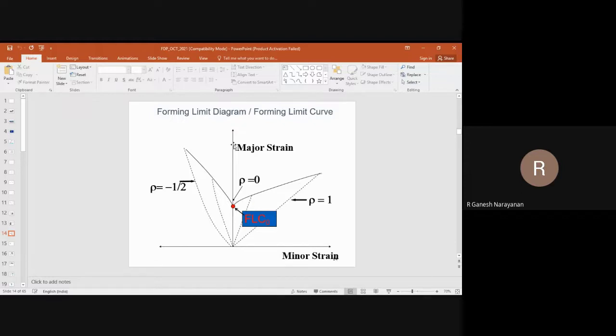Okay, once you are above this curve, you have a problem. The material can have definite physical failure. This FLC0, which I am focused on here, is nothing but one particular mode of deformation, that is plane strain mode of deformation. The limit strain in plane strain mode: if you pick up the y-axis, you will reach the red point here. Beyond that, if you deform along that y-axis itself, where minor strain is 0, you will have failure. This is the least window you have in the entire forming limit curve.